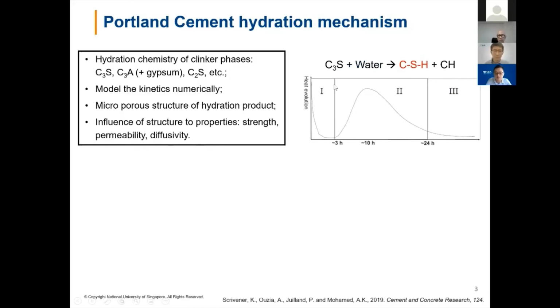Now, to give you an example, C3S is the most important clinker phase in Portland cement. When it meets with water, it will produce C-S-H and CH. C-S-H is the most important binding material in our modern concrete. This reaction can be classified into 3 stages. And we have a very special stage here when the hydration rate of C3S is very low. This stage gives us the time window to cast concrete, to place concrete, and to pump concrete. However, we're not completely sure what leads to this very slow reaction rate. We also don't know what triggers the termination of this period, so that hydration enters an acceleration and then a deceleration period. All of this still remains mysterious to us.